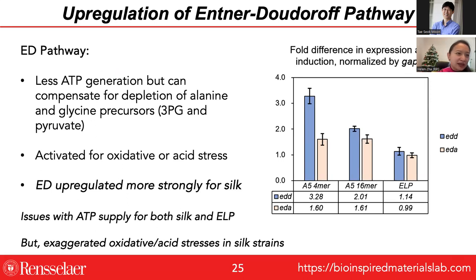We also see an upregulation of the ED pathway. We think this is a cell's attempt to respond to the stresses that it's under. The ED pathway is uncommon; it produces less ATP than the EMP pathway, but it does require fewer enzymatic steps, so it may be providing a shorter route for amino acid precursor supply. Literature has also suggested that the ED pathway is associated with oxidative stress response. We see that for both ELP-producing strains and silk-producing strains. So clearly, for making both ELP and silk, there is some sort of issue with ATP supply in both systems. However, there is what appears to be some exaggerated oxidative or acid stress in the silk-producing strains.